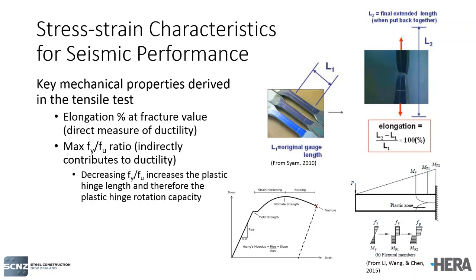The other mechanical properties that contribute to the seismic performance of the steel in an indirect way is the Fy over Fu ratio. If we decrease the Fy over Fu ratio, which means that we increase the distance between the yield stress or strength and the ultimate strength, we actually end up increasing the plastic hinge length, and therefore the plastic rotation capacity increases. To illustrate how that works, if we look at a simple cantilever beam, we've applied a point